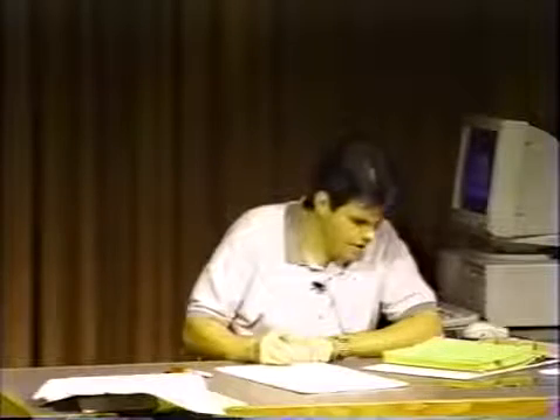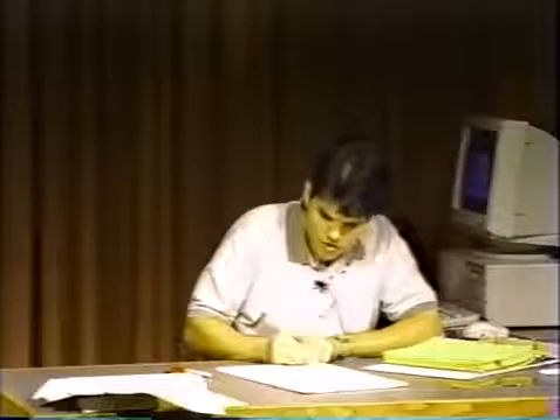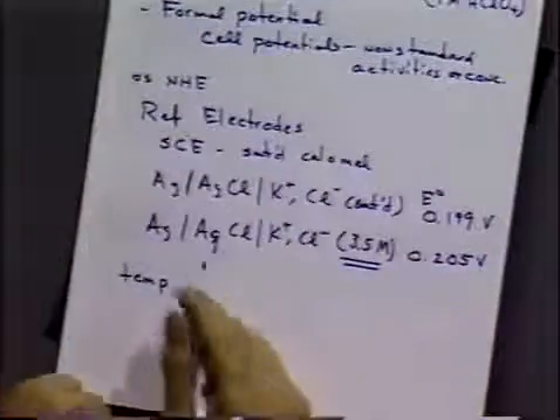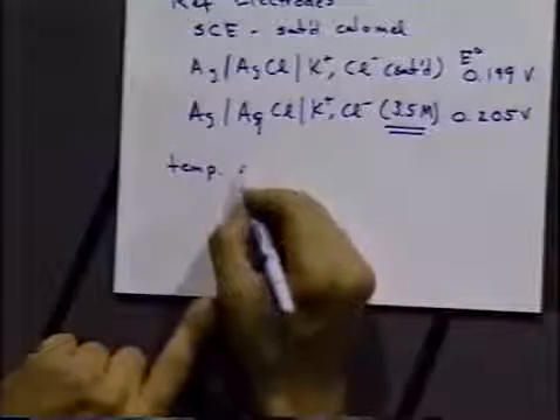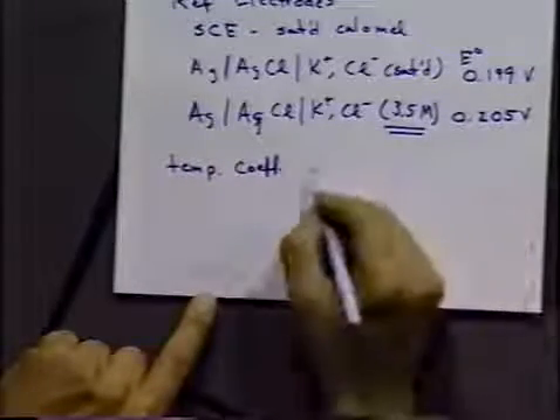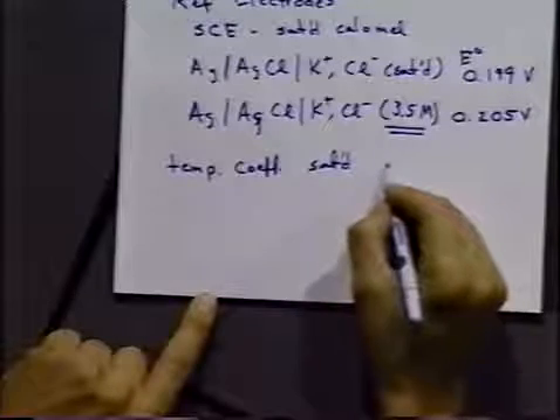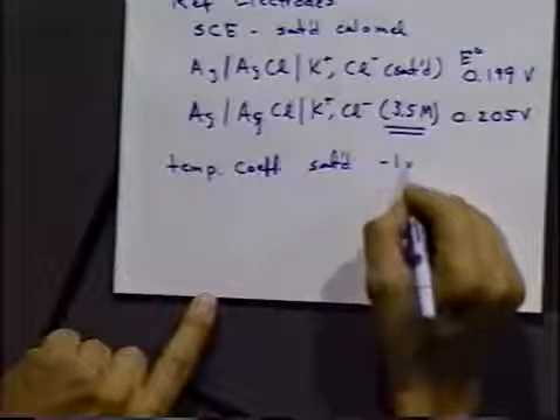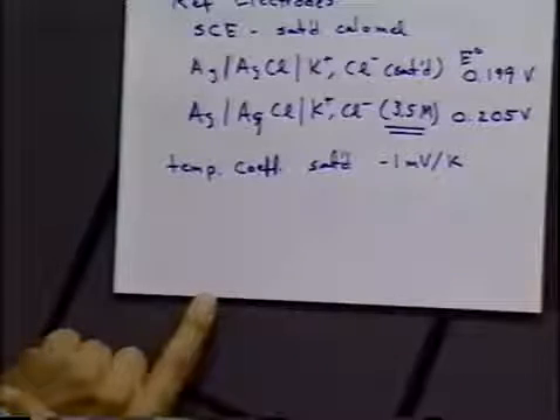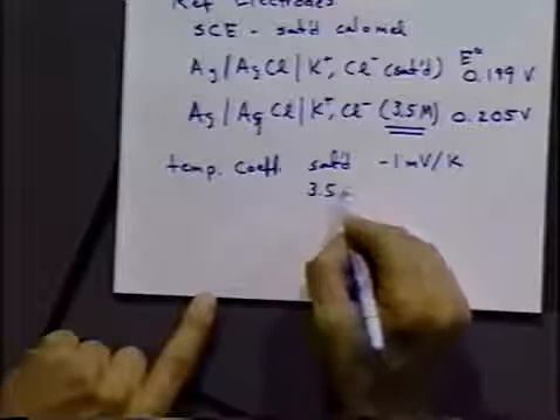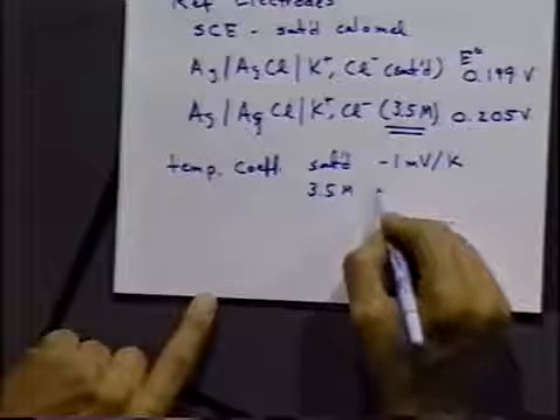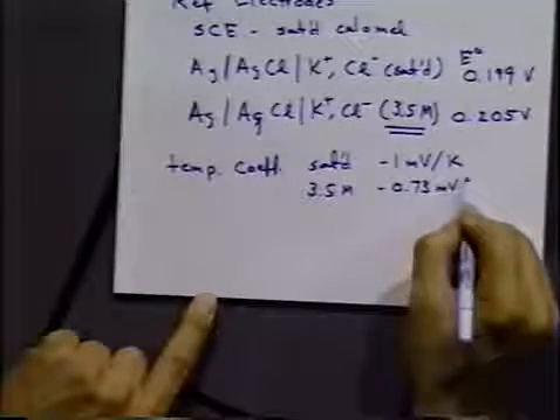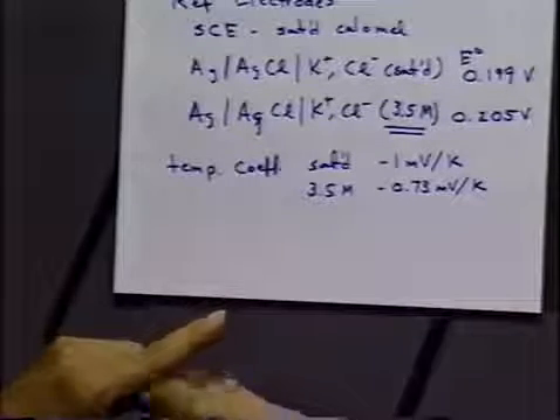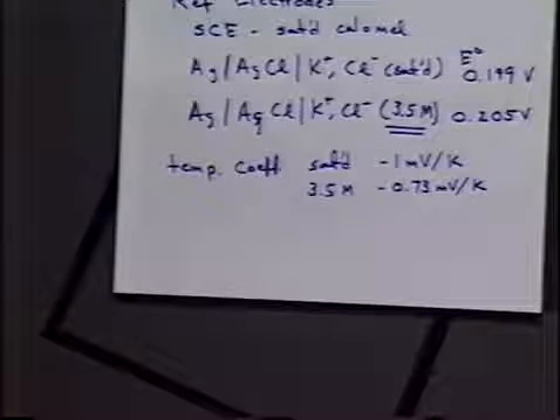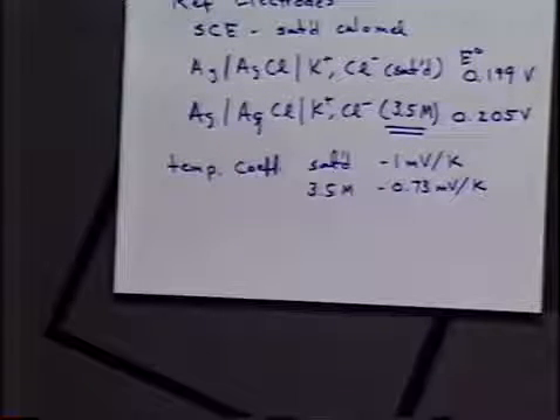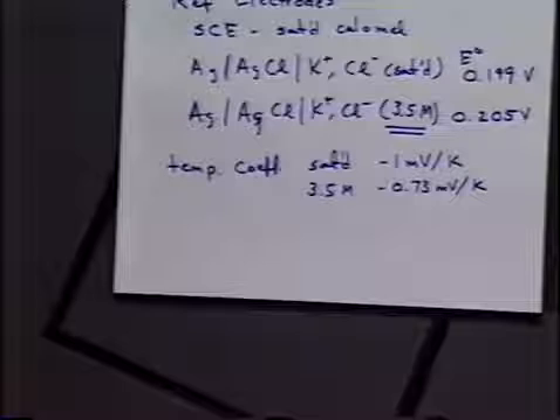I'll just give you the reason for that: there is a temperature coefficient. And for the saturated system of silver chloride, it turns out that the temperature coefficient is about minus 1 millivolt per degree Kelvin. And for the 3.5 molar solution, it's about minus 0.73 millivolts per degree Kelvin. In other words, there is quite a difference in the potential change with temperature for the two systems. And it turns out to be important.